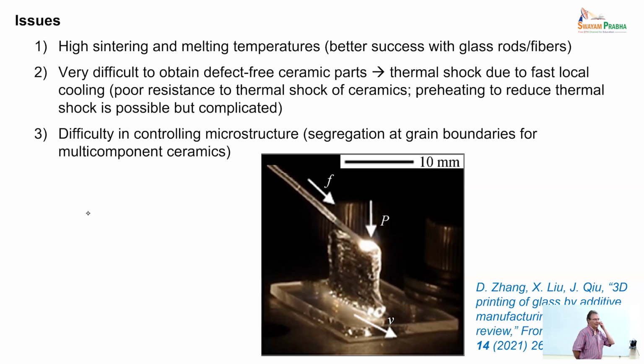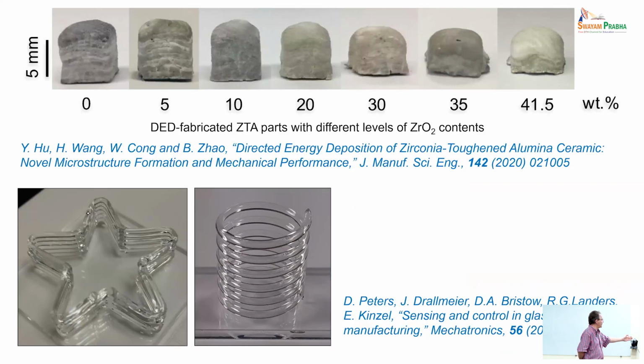The melting temperature of silica is about 1700, but the glass transition temperature is about 1200 degrees. So you simply need to go to, let's say, 1400 degrees, and then you can have localized melting of your glass. And you do not have thermal shock because of the almost zero coefficient of thermal expansion. So you can see here some successful examples for glass.